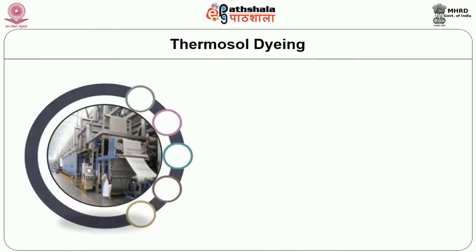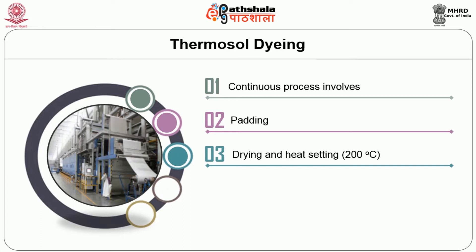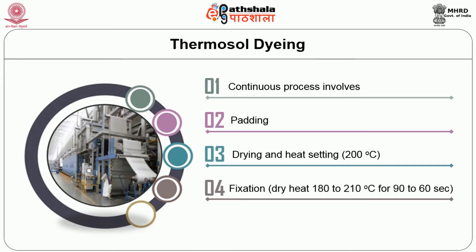Thermosol dyeing is a continuous process in which dry heat is utilized effectively in the dyeing of synthetic textiles. It involves padding of fabric through a dispersion of the dye, drying, and heating for about 1 minute at 200°C. At this temperature many dispersed dyes are molten whilst the fibre is plastic with its chain molecules vibrating vigorously — the fibre attains its glass transition temperature at 200°C. The dyeing consists essentially of a liquid dye dissolving in a fibre which itself is like a viscous liquid, hence the name thermosol process. The mechanism of thermosol fixation is the same as for exhaust dyeing — the dye is dissolved directly in the fibre when exposed to temperatures of the order 205°C.